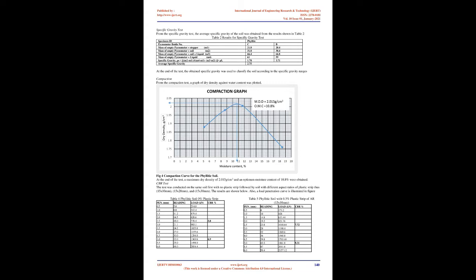Specific gravity test. From the specific gravity test, the average specific gravity of the soil was obtained from the results shown in Table 2, results for specific gravity test. At the end of the compaction test, a maximum dry density of 2.015 g/cm3 and an optimum moisture content of 10.8% were obtained. CBR test.